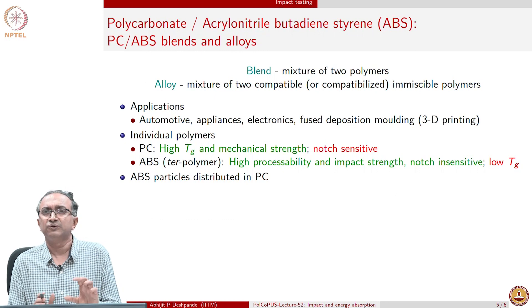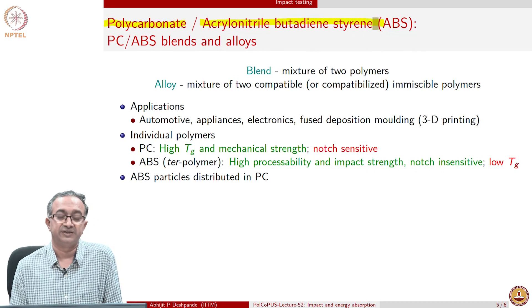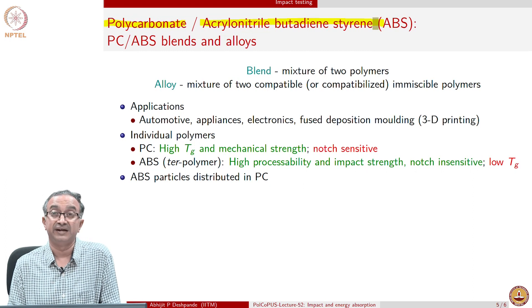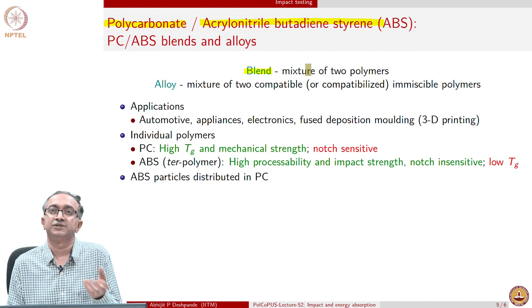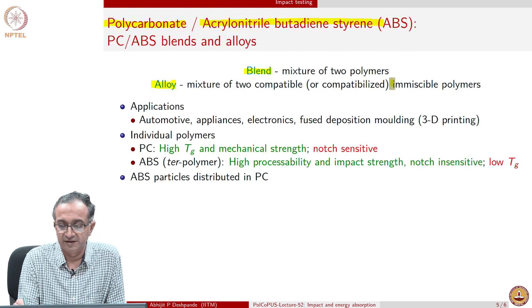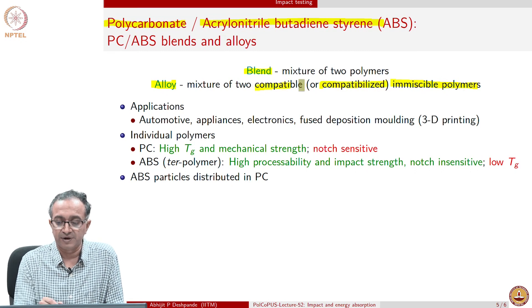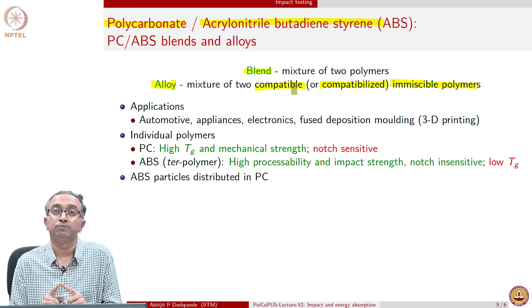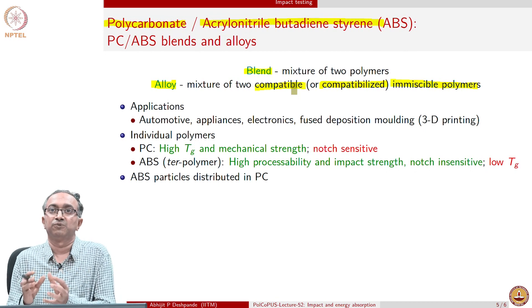Before looking at impact strength, let us look at an example application material: polycarbonate and ABS — acrylonitrile butadiene styrene — blend and alloy systems, which are very popular. A blend is a mixture of two polymers — miscible, partially miscible, or immiscible. We refer to an alloy when we have immiscible polymers with compatibilization between the two phases — so compatible, immiscible polymer blends. Even though the two polymers are immiscible, at the interface there is some interaction between the macromolecules of one with macromolecules of another.